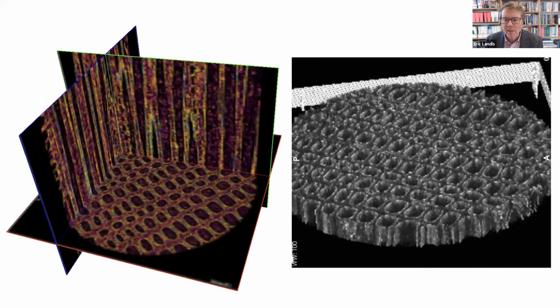This shows X-ray CT images. Unfortunately, I committed the cardinal sin of imaging, which is I did not put a scale bar. But these are on the order of maybe 20 to 50 microns across, depending on, they are definitely visible with the optical microscope. So the cellular structure, you have the cell wall, and then you have a hollow, what's referred to as a lumen.